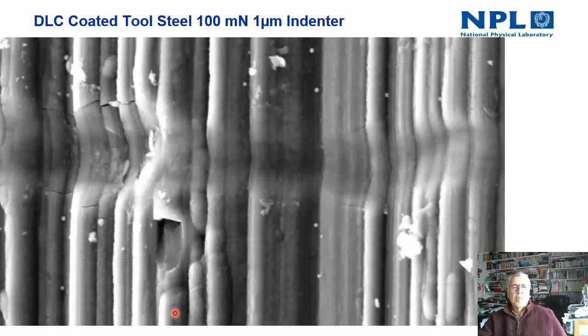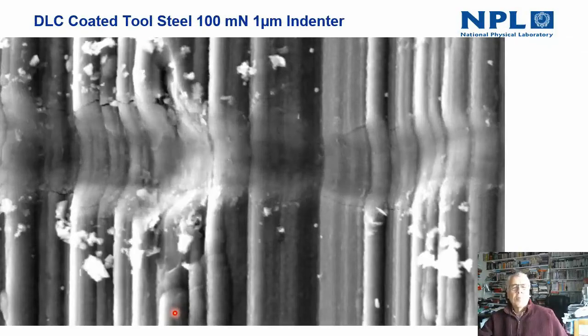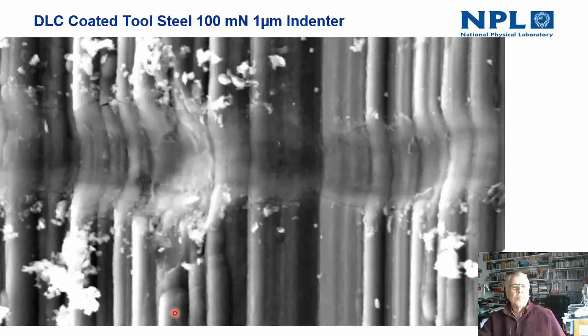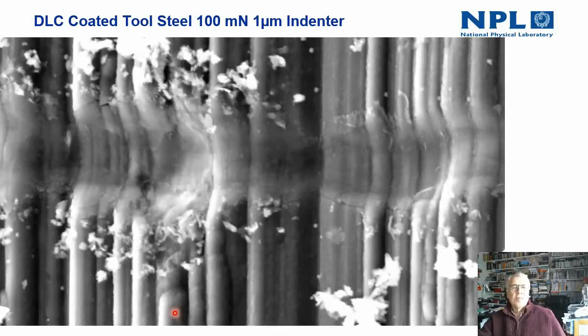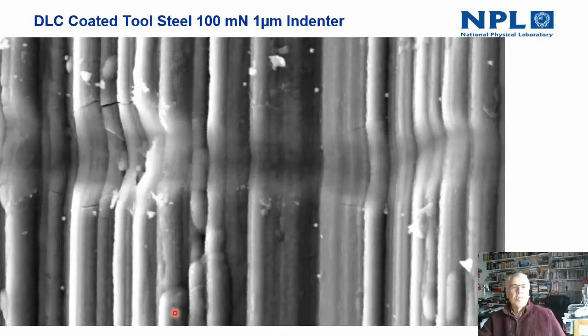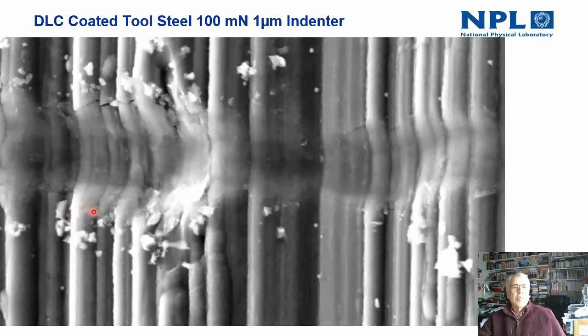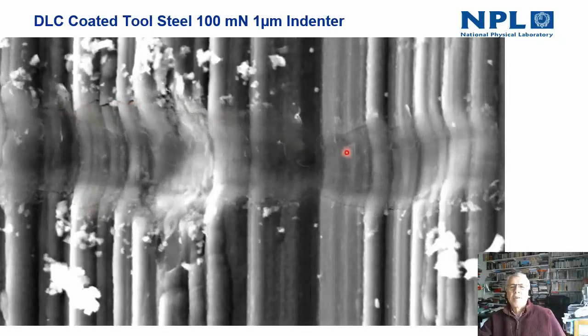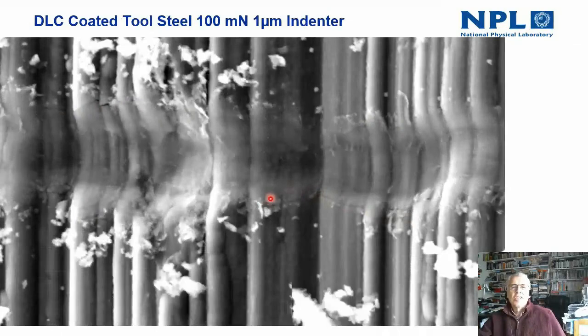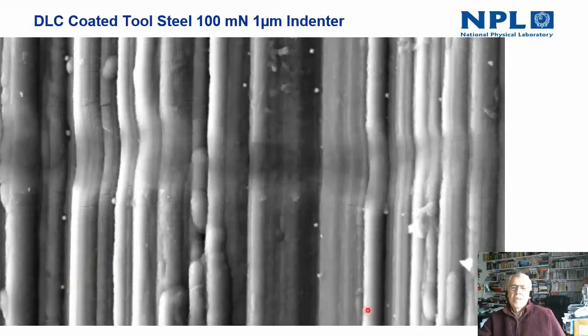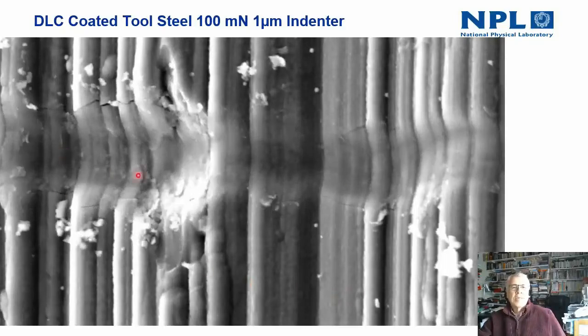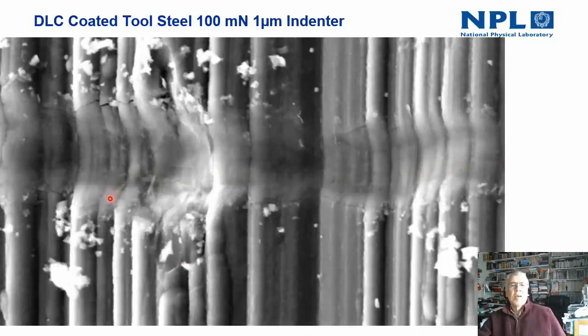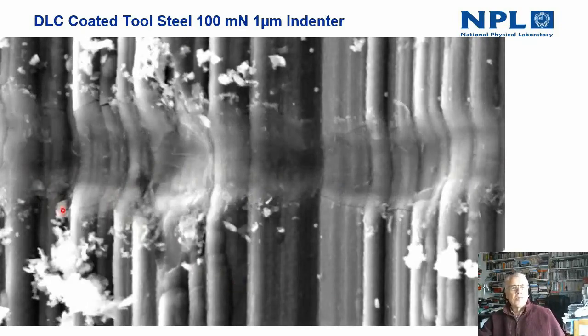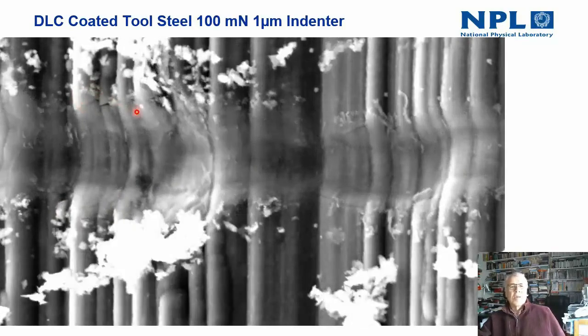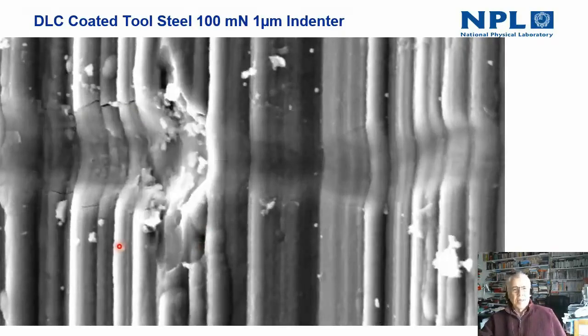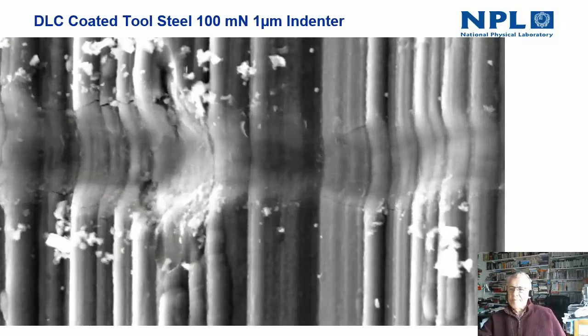When you contrast that with a coated sample of the same material in the same condition, you can see that the coating really does reduce damage considerably. Having said that, what is interesting here is cracking that you can observe along the edge of the scratch, and this is like eggshell cracking, where it's deformation under the surface in the substrate that causes high stresses along the edges of the scratch in the coating and then lead to coating failure.